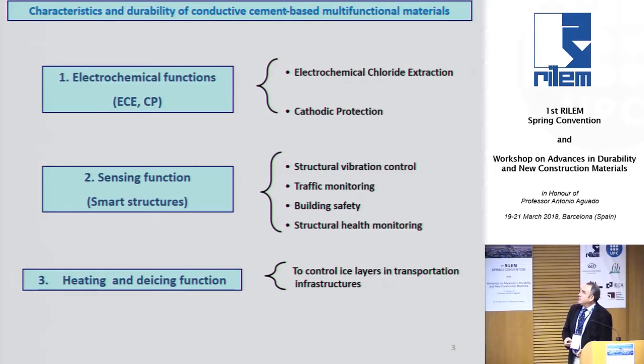Possible functions are electrochemical ones: electrochemical chloride extraction, cathodic protection. The possibility of using a conductive cement-based material as an anode in the application of this electrochemical technique is really very interesting from the point of view of durability.